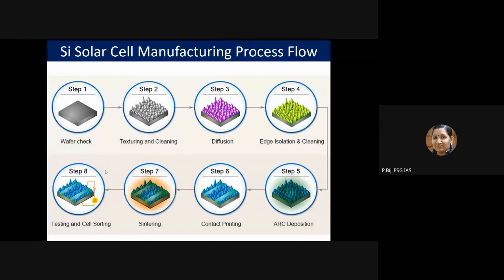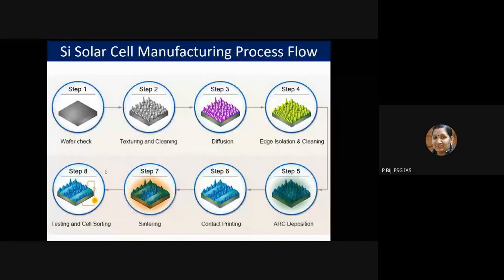Following the pre-check, the front surface of the silicon wafers is textured, basically to reduce the reflection loss of the incident light. The most common technique is random pyramidal texturing. After texturing, the wafers undergo an acid cleaning, in which any post-texturing particles remaining on the wafer are removed from the surface, because the next stage is diffusion. Diffusion is basically doping, to make the silicon wafer more electrically conductive. There are two methods for diffusion. The first one is solid state diffusion, and the other is emitter diffusion.